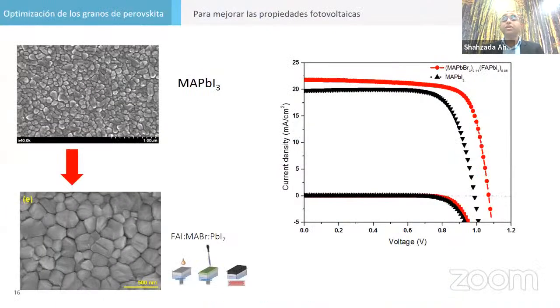When we started to work with perovskite in 2012, our grain size was very small because at that time we were working with only methylammonium lead triiodide. But after working for almost 10 years, we have worked on different kinds of composition engineering and different types of solvent engineering approaches to make our crystals larger. Now we have crystals of more than 1 micron size, even much larger. And why do we do it?